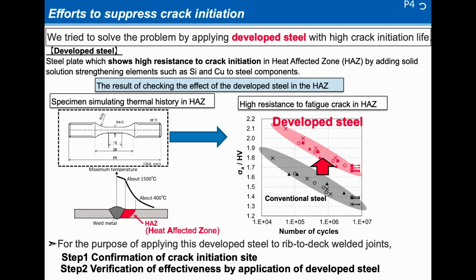In this situation, I'll explain our efforts. We try to solve the problem by applying the developed steel with high crack initiation life. I'll explain the developed steel. This steel shows high resistance to crack initiation in the heat-affected zone, HAZ, by adding solid solution strengthening elements such as silicon and copper to the steel components. This shows the result of checking the effect of the developed steel in the HAZ. The welded zone is affected by the heat caused by welding, so the property is changed.